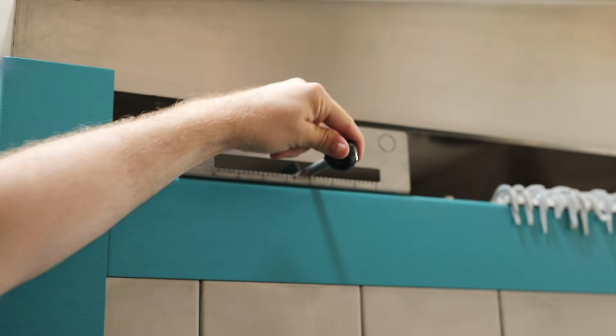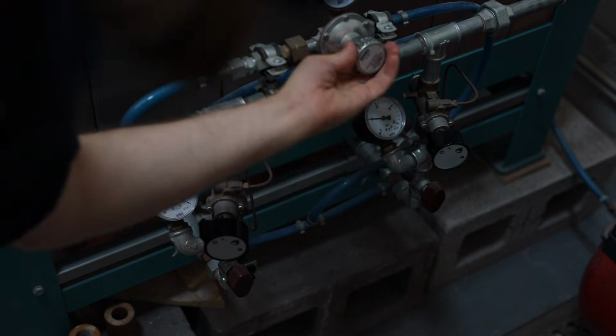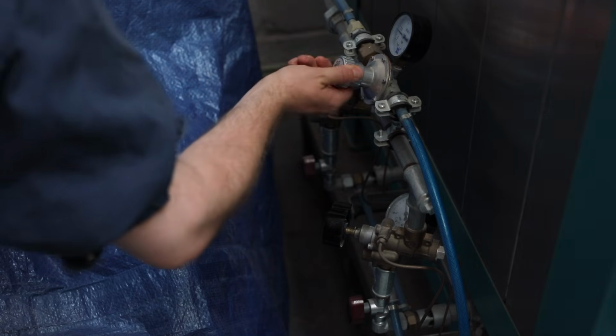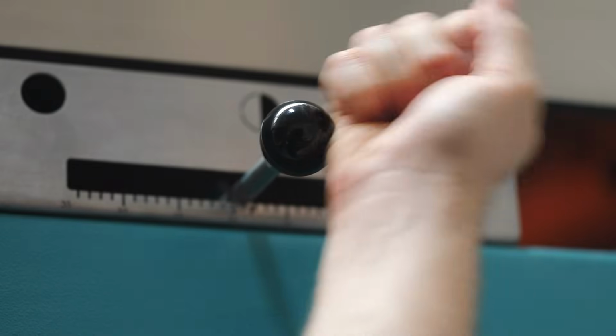So at the beginning it's taken slowly, and then at 860 degrees precisely, I initiate the reduction atmosphere by sliding the damper to be half closed and increase the gas pressure and air pressure. This causes too much fuel to accumulate in the chamber, with there not being sufficient oxygen present for it to burn efficiently. This means the atmosphere ends up stripping oxygen away from the clay and glazes themselves, thus creating colours and textures that you can't quite easily replicate with an electric kiln.